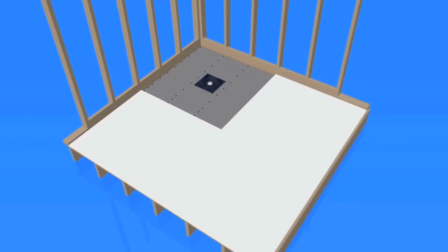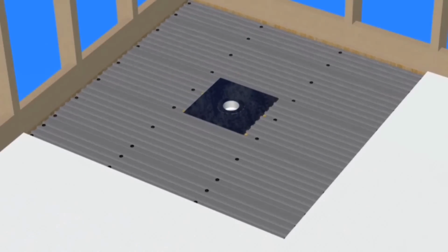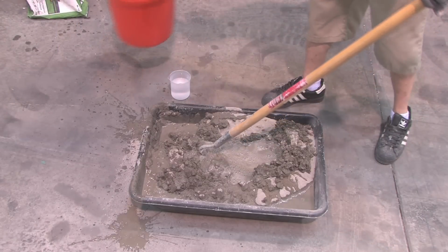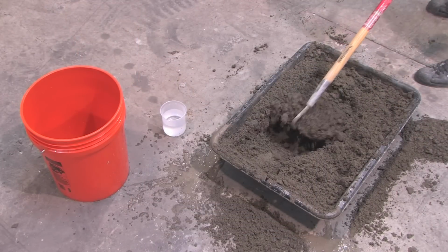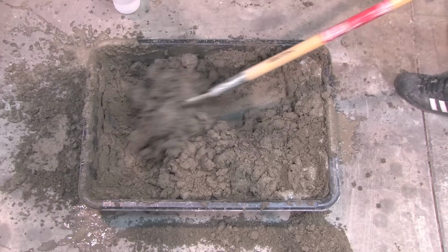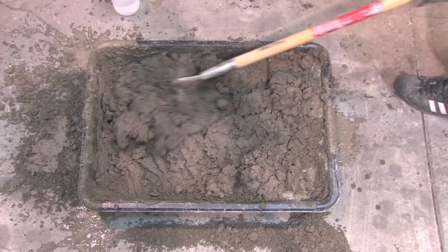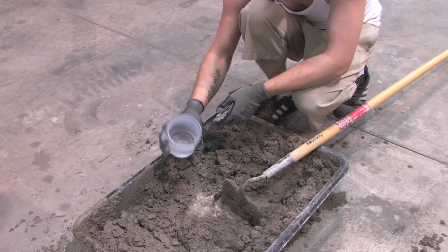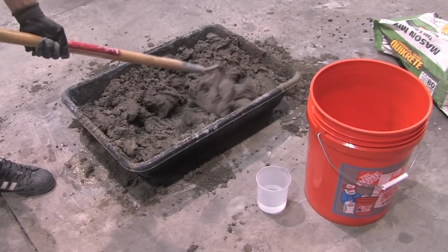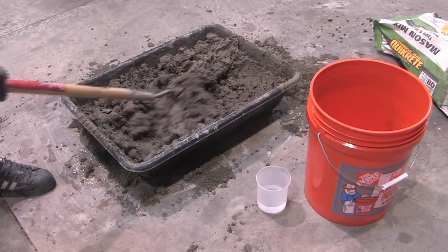Use a wetter than normal mortar mix to aid in screeding the slope on the TI ProBoard, but do not overwater the mixture. That could cause cracks. Add no more than 12 additional ounces of water to the normal recommended amount to achieve a workable mix. Add water in thirds, mixing thoroughly after each addition. Not all 12 ounces will be necessary. Check as you do it.